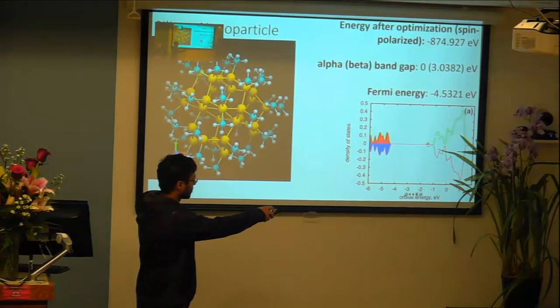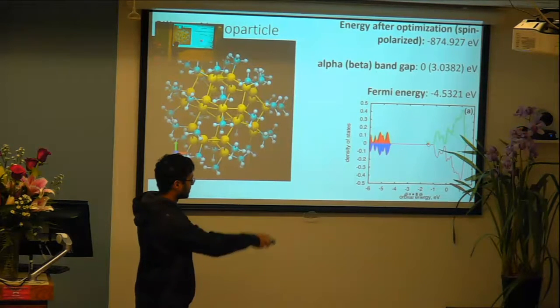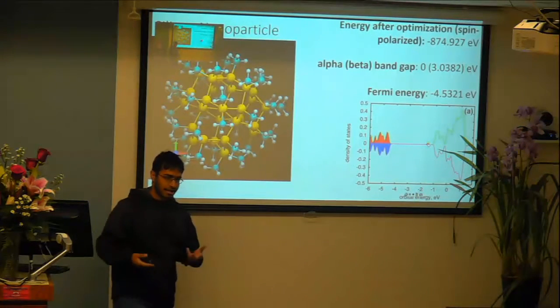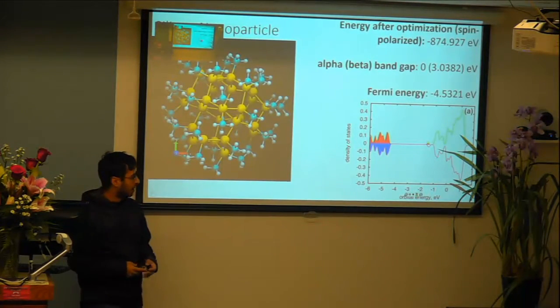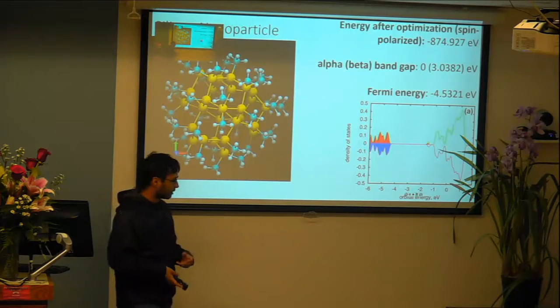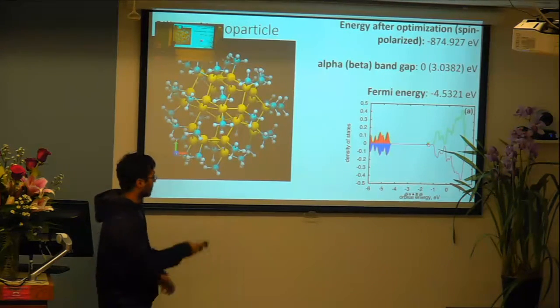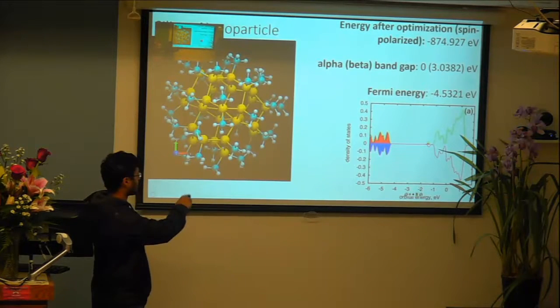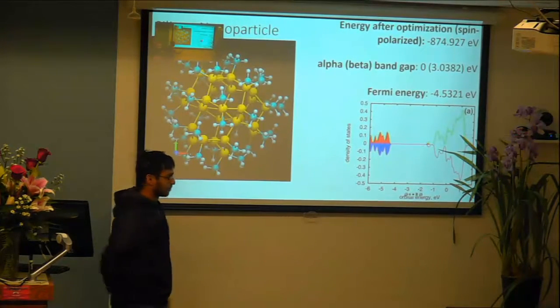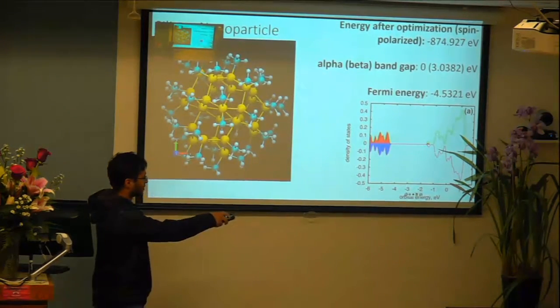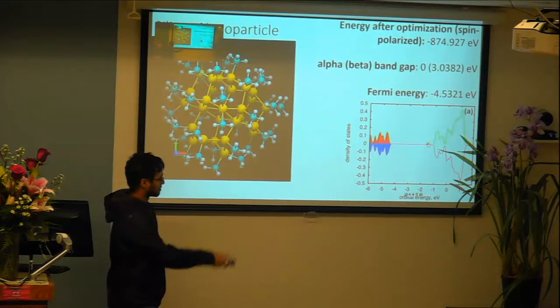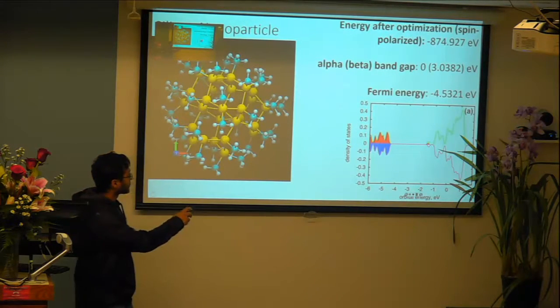So we can see that there are some electrons in the conduction band here, and this is likely because the model was not oxidized. So further work could be done in order to actually oxidize this silicon nanoparticle and remove electrons from the conduction band. And we'll see a consequence of not oxidizing this model in a couple of slides.